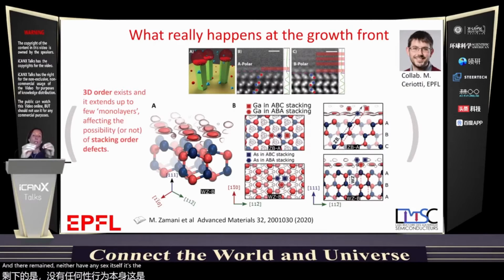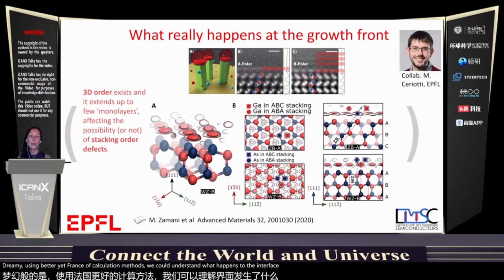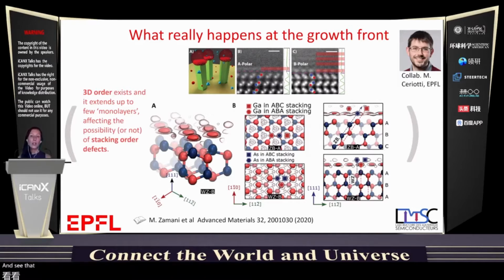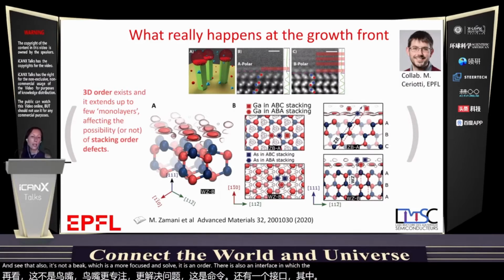It's twin-free gallium arsenide. So by just following our scientific curiosity and really using very advanced calculation methods, we could understand what happens in the interface and see that it's not that liquid is amorphous and solid is ordered. There's also an interface in which the order exists, and interesting things happen there.